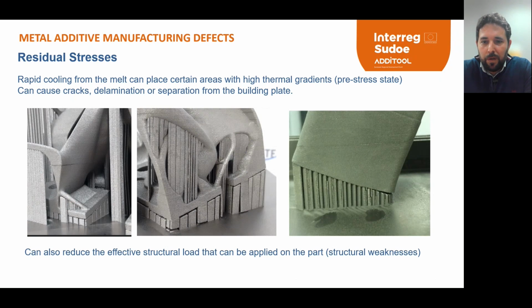Residual stresses appear with rapid cooling of the melt pool that could produce high thermal gradient in certain areas, causing cracks, delaminations, or separation of the building plate, as you can observe on this image. Moreover, and it's also important, residual stress can reduce the structural effectiveness. That is why it's so important to perform thermal treatment. For instance, stress relief.